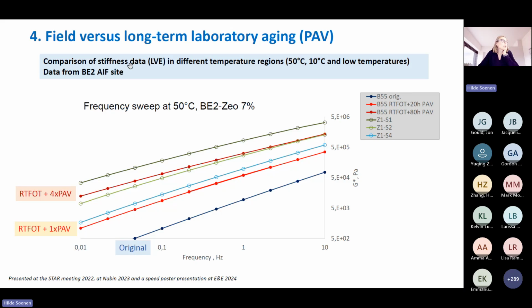So we looked in this case at stiffness data at different temperature regions for one section. For this Belgian section, we still had the original binder. And this is again the one with zeolite with the 7% voids. And you see the comparison at 50 degrees here. So the original, this is the standard aged, so RTFOT and 1 times PAV. And then we did a continuous aging up to 4 times pressure aging vessel. And you can see these 3 are the field aged slices, that the 4 times PAV comes close to what you see in field aging at 50 degrees.